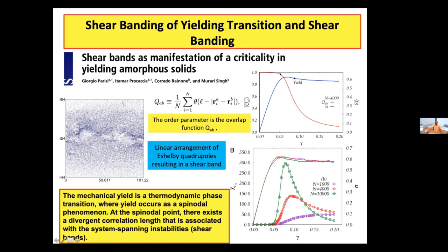And this decay becomes even sharper if you take a larger and larger system size, telling us that this replica order parameter is probably a good order parameter to characterize the yielding transition in this kind of solids. They also looked at the corresponding susceptibility. Susceptibility shows a large peak, and the peak increases with increasing system size, signaling a possible divergence at large system size. So this tells us that the yielding transition is probably some sort of thermodynamic non-equilibrium transition.